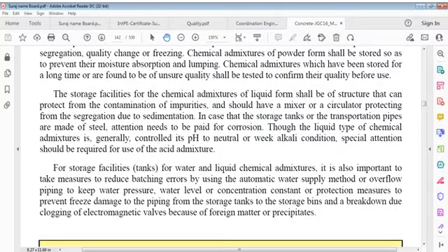Storage facilities for chemical admixtures of liquid form shall be structured so as to protect from contamination by impurities, and should have a mixer or a circulator to protect from segregation due to sedimentation. In case storage tanks or transportation pipes are made of steel, attention needs to be paid to corrosion. The liquid type of chemical admixture is generally controlled to a neutral or weak alkali pH condition. Special attention is required for use of acid admixtures.